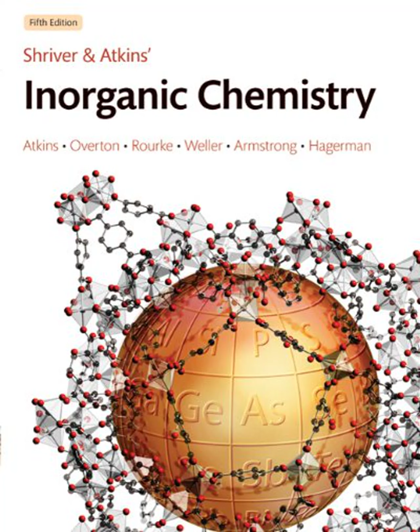Like the pre-edge region. Right. Just below the main edge, you might see small peaks corresponding to exciting a core electron into empty valence orbitals. The position and intensity of these pre-edge features can tell you about the oxidation state and coordination geometry of the absorbing atom. And just above the edge? That's the XANES region, X-ray absorption near-edge structure. This part is very sensitive to the oxidation state and the local coordination environment. It often acts like a fingerprint for a specific chemical site. There's also NEXAFS, near-edge X-ray absorption fine structure, which is particularly useful for studying molecules adsorbed on surfaces, as it can tell you about their orientation.